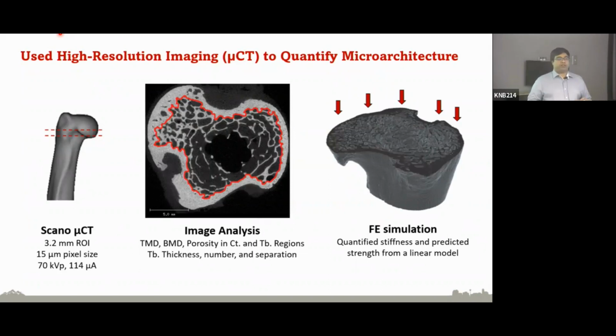The way this simulation works is that I take geometry information from the scans, and then I apply assumed reasonable material properties for the bone tissue. I then tell it how I think this section of bone might be loaded. So for this particular analysis, I held one end and we pushed down on the other, a fixed amount of displacement. And then we used the principles of continuum mechanics to understand how the bone would locally and globally react to that sort of loading environment. In this particular work, I then took that information and got a measure to estimate overall stiffness and strength of the bone.